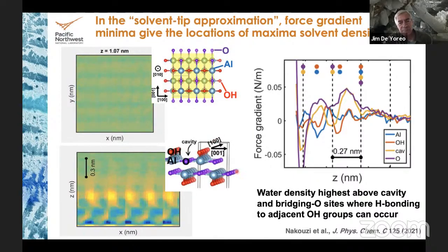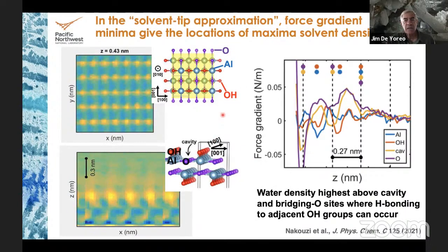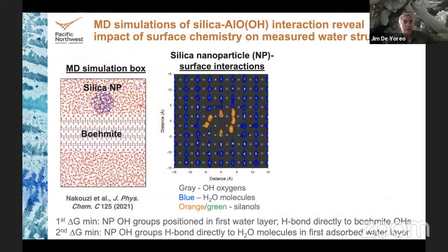Now, the question is, is it really that simple? Is the tip really just like a solvent molecule? And the answer is no, it's not. So we did simulations. This is Sebastian Kerisit's work again, using a silica nanoparticle against a boehmite surface. The silica nanoparticle represents the oxidized silicon tip of the AFM. And what we found is that if you look at the first hydration layer, it's actually the hydroxyl groups on the silica nanoparticle interacting with the hydroxyl groups on the surface that define the first maxima or minima.